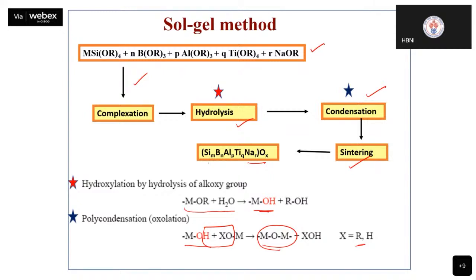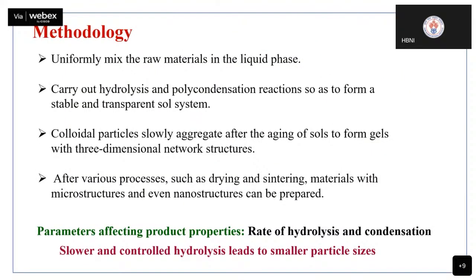Best part about this synthesis route, there are very few routes in which you want to have a multi-elemental product and you want to make it in the same stoichiometry and in bulk. There are very few routes which can ascertain that. With the sol-gel method, multi-elemental composition can be made with good compositional control. So methodology, I've already told you: you mix the raw material, you carry out hydrolysis, polycondensation, so that you get a sol. Then this colloidal particle will slowly aggregate after aging of sols, and they will form gel, which is a 3D network, and you dry your gel and you sinter your gel, then you can get materials with different microstructure, and even nanostructures are possible. And this particular thing will depend upon how you maneuver your drying and sintering process.